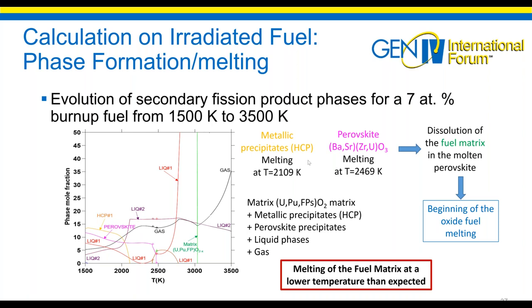So here you can recognize one family of fission products called the metallic precipitates, so the ones that are metals. And you can see here that they are stable at 1,500 K, but when you start to increase the temperature, they will melt. And the melting happens at 2,100 K. But also, you can find what we call perovskites. That is, if you recognize the formula, the gray phase that I was talking about before. And you can see that they will melt at nearly 2,500 K.